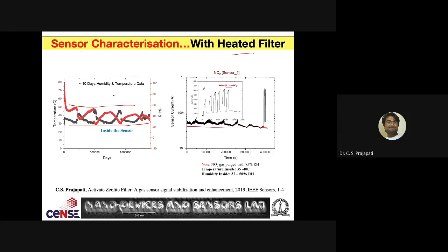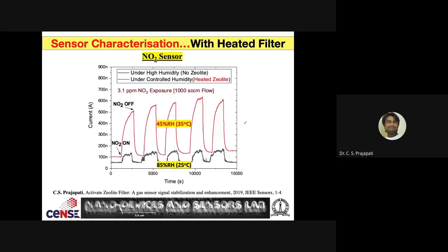You don't want a lot of noise in the background; you want a higher signal to noise ratio, by the way. So this is what we are getting. When we compared, when you don't have zeolite or heating, you have 85% of whatever moisture is there coming onto the sensor. When you have a filter in between, only 45% is coming. In the room or in the environment it will vary, like 40 to let's say 85, and in the rainy season it may go to 95% RH.